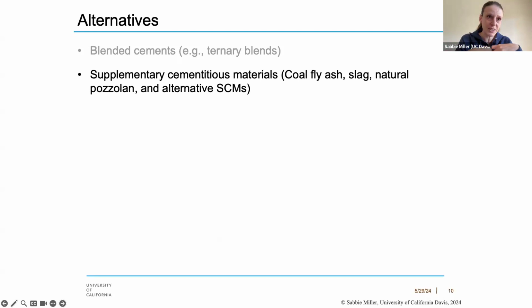Other types of blended cements that you might come across include ternary blended cements. These oftentimes are leveraging still some of that limestone filler that you're going to have for your Portland limestone cement, but also a pozzolan. And there's actually been some studies that have shown there's a beneficial interaction between the interground limestone and our pozzolans that could lead to very similar mechanical performance out of our concrete, great durability characteristics, but possibly slightly different workability conditions.